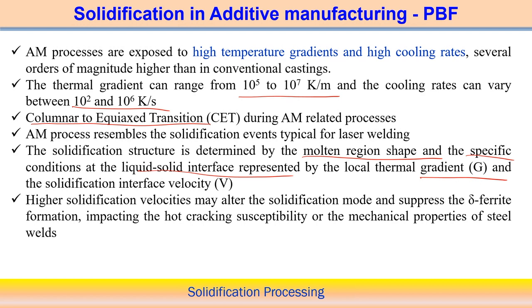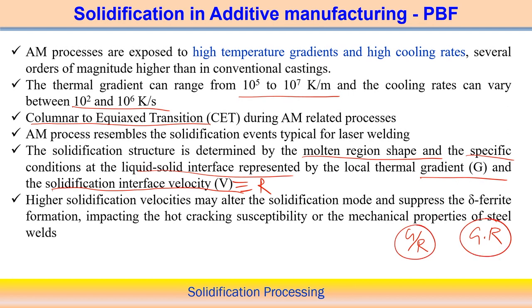The growth rate R always corresponds to the scanning speed or welding speed in this process — the solidification interface velocity is equivalent to the laser scanning speed or arc speed. Both G and R are solidification parameters. We investigate the ratio G/R, which decides the mode of solidification, and G×R, which decides whether fine or coarse structure will form.